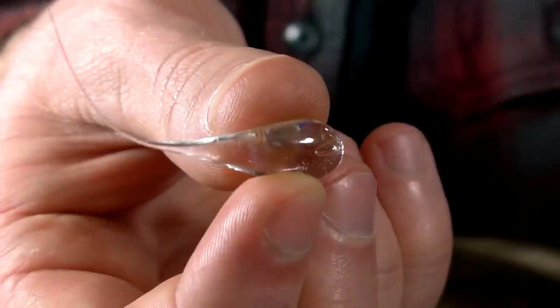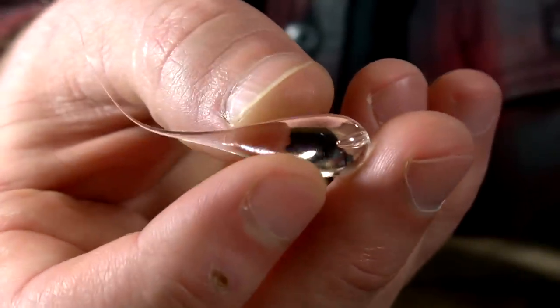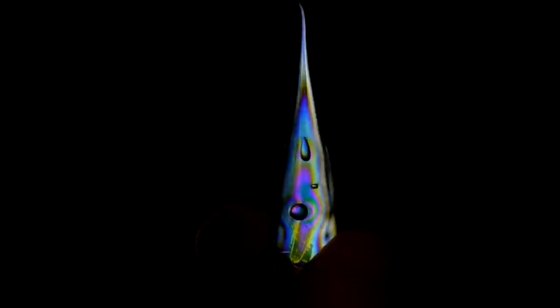The result is a perfect drop with a massive amount of internal stress caused by the rapid change in temperature. Backlighting the drop with the polarized light from a computer screen and placing a polarizing filter over the camera lens reveals waves of color that indicate the stresses present.